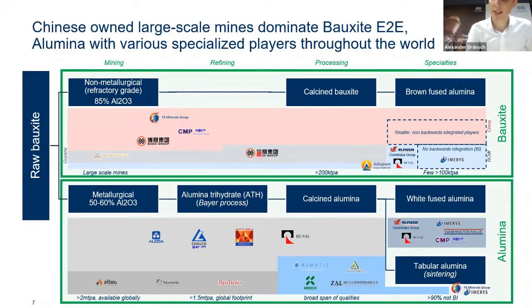And this is, in this case, already at the calcined alumina. So this is when you take the alumina and you calcine it to get exactly the properties that the end-use industries want. And the most well-known actually is Almatis that is doing that. And we, for example, Magnesita, buy calcined alumina for our finished products.